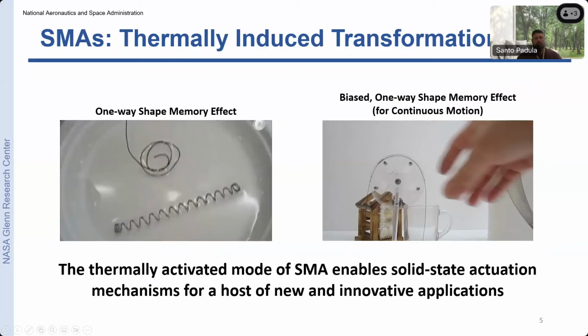In these videos, what we're going to see is a couple of examples of what we call the thermally induced transformations. So in shape memory alloys, we can utilize this phase transformation that exists in two different modes. We can thermally induce the transformation to create shape recovery, or we can utilize it in another mechanism, which we'll show later, called the mechanically induced transformation, where we can apply loads and stresses reversibly, and we can create large deformations reversibly just by loading and unloading the components.